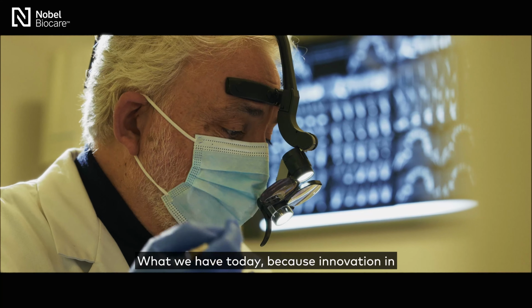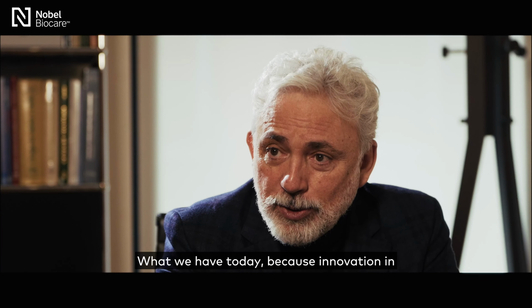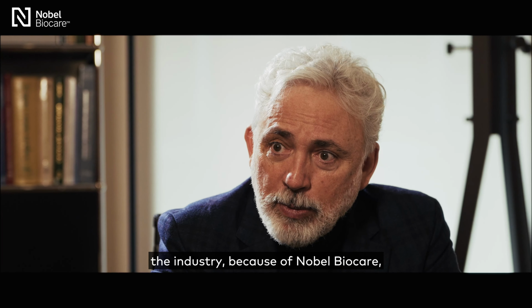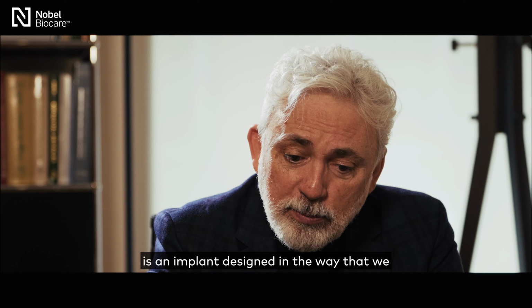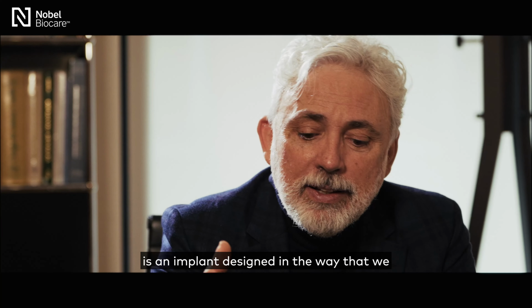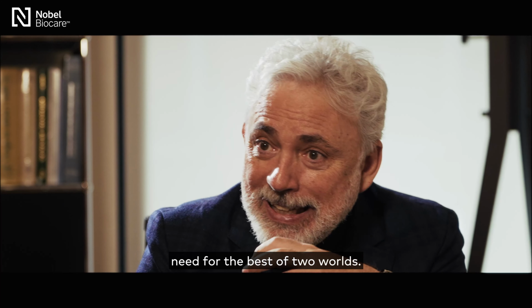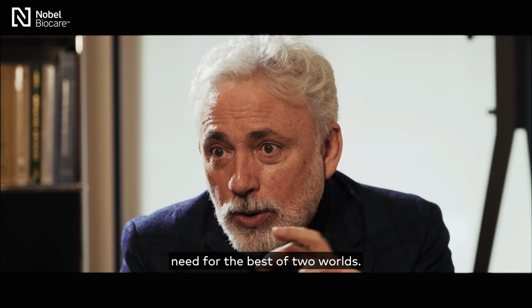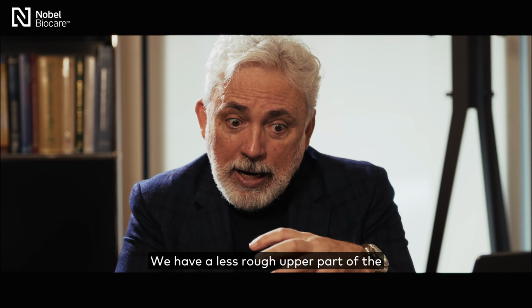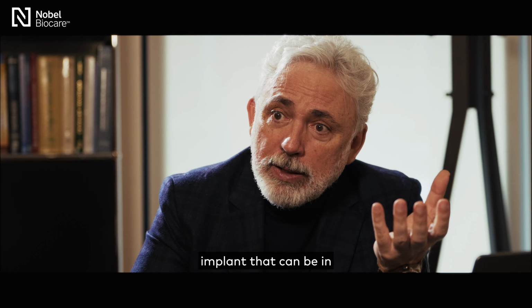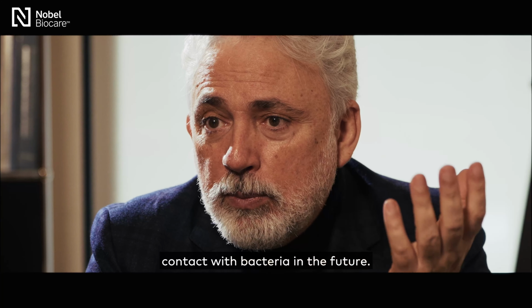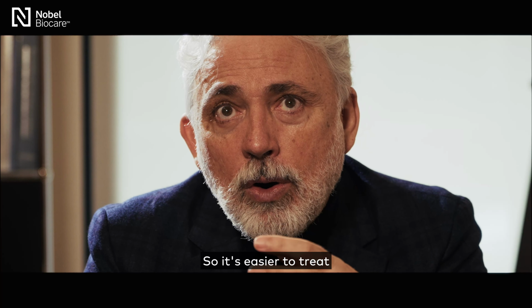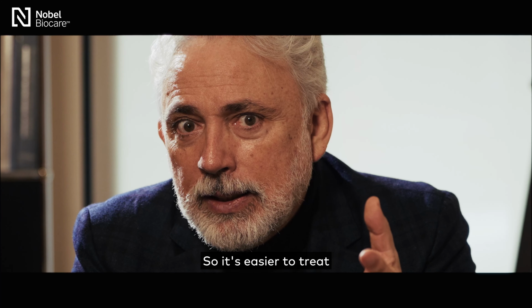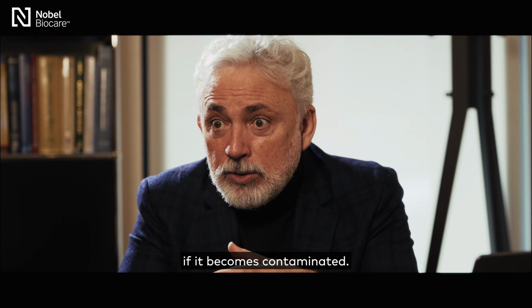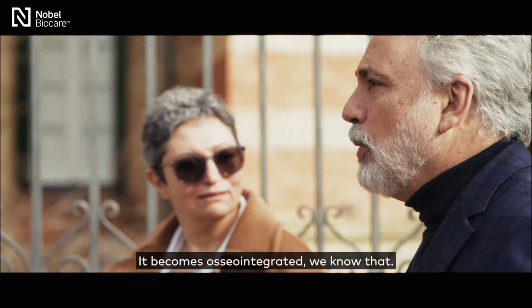What we have today, because of innovation in the industry, because of Nobel Biocare, is an implant designed in a way that we have the roughness that we need, the best of two worlds. We have a less rough upper part of the implant that can be in contact with bacteria in the future, so it's easier to treat if it becomes contaminated. It becomes osseointegrated, we know that.